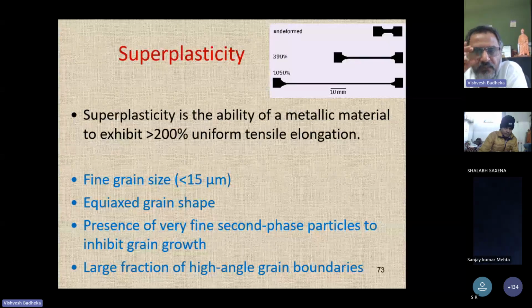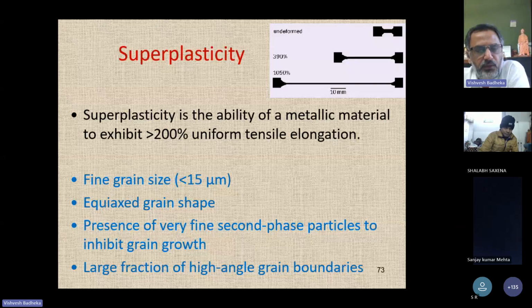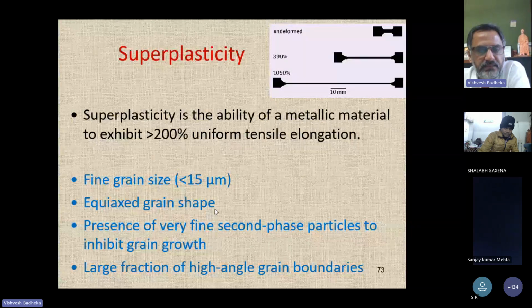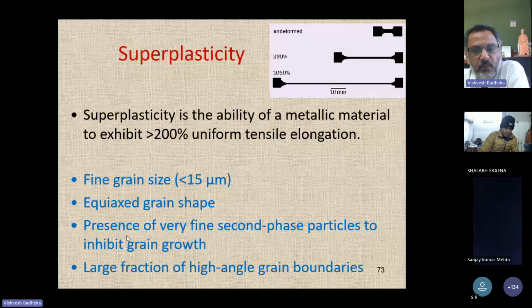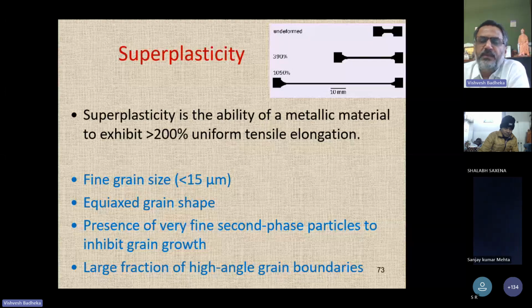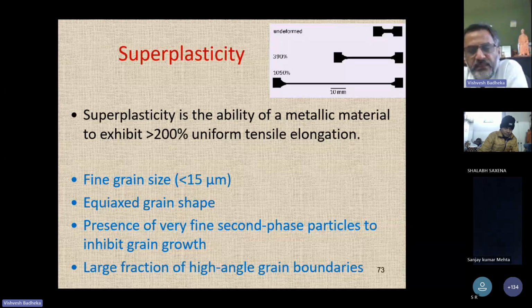So with the help of this concept of FSP, the grain refinement will take place. That is one, because you are running the FSP tool. Additionally, your grains become equiaxed. Additionally, the third important thing: since it is aluminum, you have some precipitates. These precipitates are of different size and different order. But after FSP, these second phase particles become very fine. I mean, they are also fragmented with the help of FSP, and after that fragmentation, they uniformly distribute into the matrix.